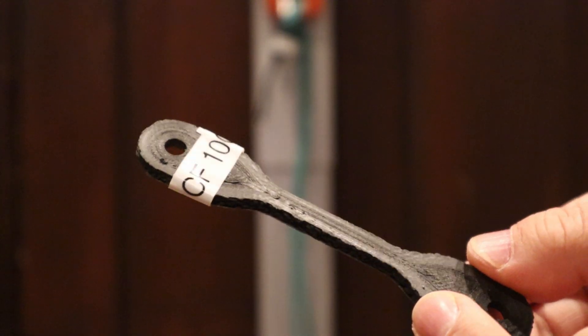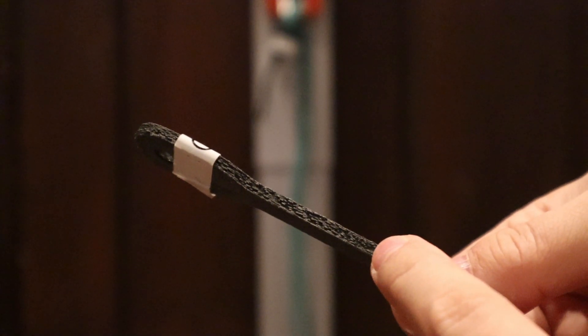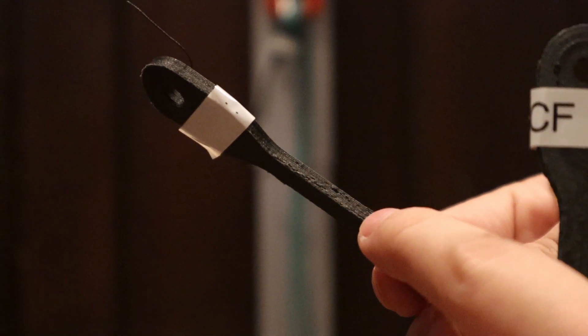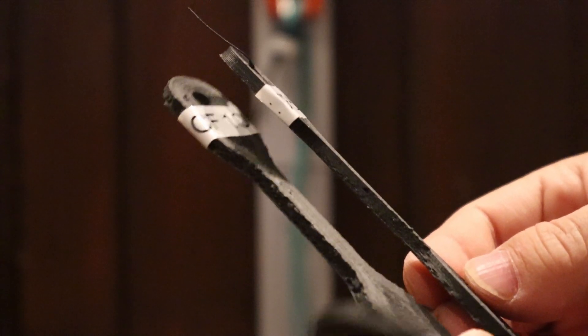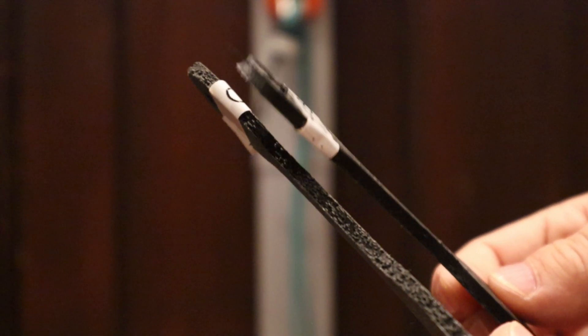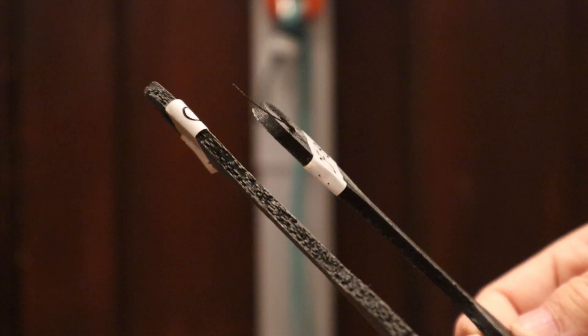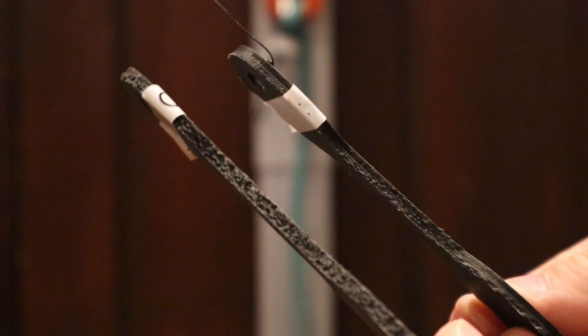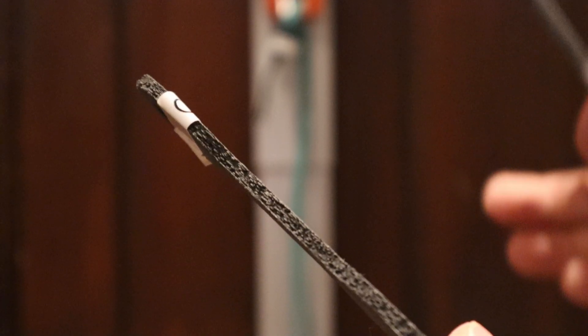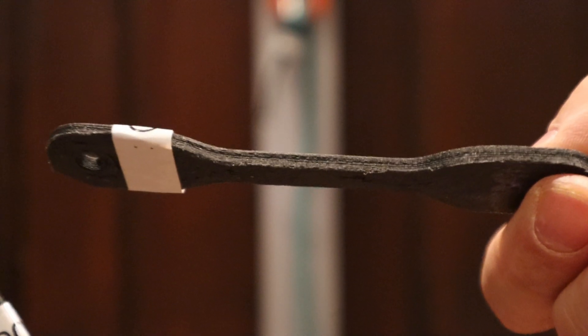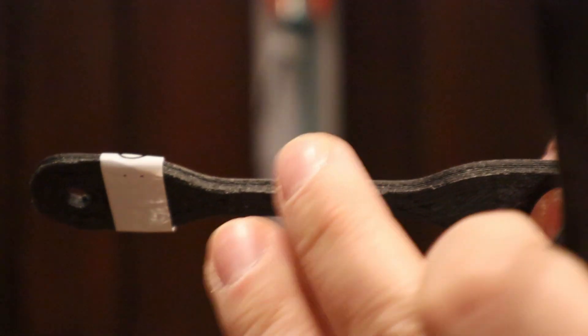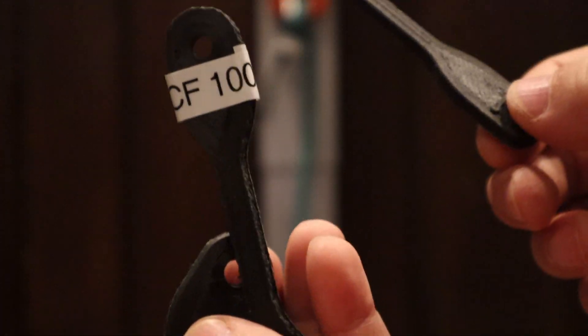This is the first print that I made with the carbon fiber filament as soon as I got it. It kind of puffed up from the water inside turning into steam, so it was printing more material than it thought it was. In order to counteract that, I turned my extrusion multiplier down to 80%, and that cleaned up the surface finish. When you print it in its wet state, it puffs up an additional 20%. And that's not a good thing, because when you turn a material into a foam, it loses strength rapidly. You would think that if you have a foam that's 50% the density of a solid material, that it might be 50% as strong. Well, no, that's not the case. It's actually more like a third as strong.